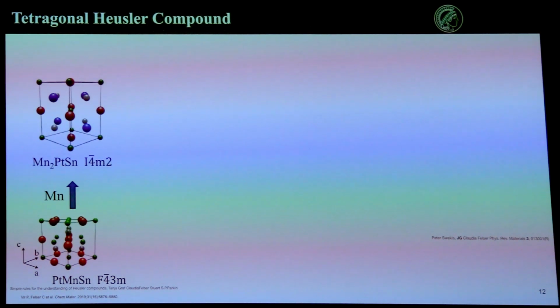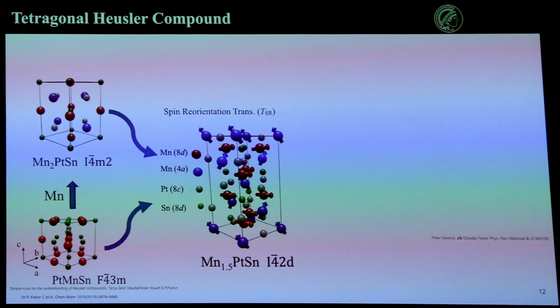And then we want to say, okay, let's take a little bit more manganese out. And what happens is you get this superstructure that forms. And this is the structure that was shown for this phase diagram. And some very interesting things happen in both of these two compounds, which are very similar. You will see in some slides earlier exactly how this structure fits into here, but this superstructure has something called a spin reorientation transition. So at low temperatures, the spins do not align completely. And as you increase the temperature, there's a reorientation, and they all align either ferrimagnetically or ferromagnetically.